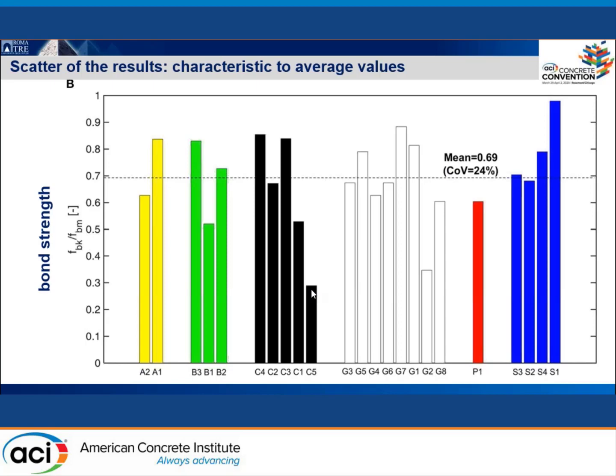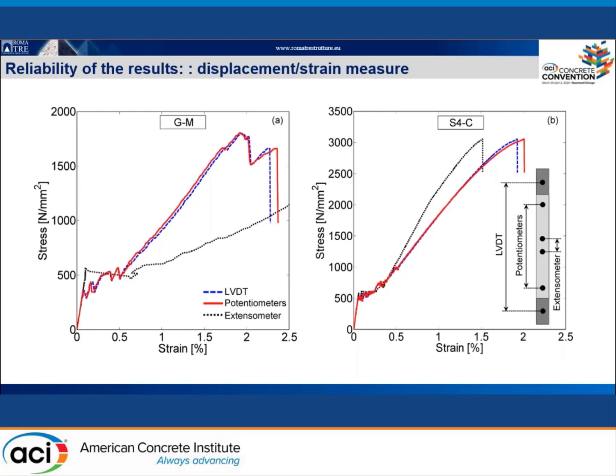Not only is it difficult to evaluate the strength of the system, but also the displacement and the strain, because like all brittle systems, since you experience discrete cracking when testing the behavior of this system, you have to define a basis of the measurement in order to get a reliable value of the average strain. Otherwise, you will completely have wrong results.